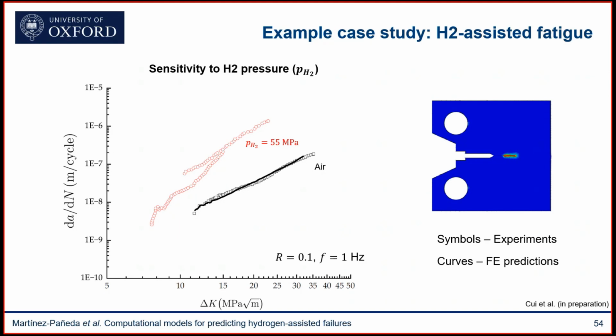The only interplay between hydrogen and the fracture resistance of this material is that fracture energy reduction with hydrogen content that I showed you before, that is well characterized for this pressure vessel steel. So we do have a proper fracture toughness versus hydrogen content curve. So I'm going to run my virtual experiment with fatigue, and this is the response that I get. So again, the symbols are the experiment, the solid lines are the computational predictions. So a very good agreement.